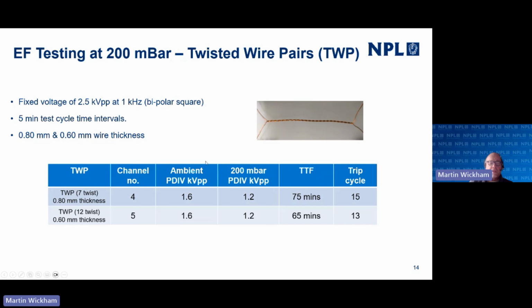So this shows some data from a simple twisted wire pair. We're testing at 200 millibar. We've got a fixed voltage in this case of 2.5 kVpp, and it's a 1 kilohertz bipolar square waveform. There are 2 wire thicknesses here. These are coated wires, and they're twisted together so that they're in close proximity to each other.